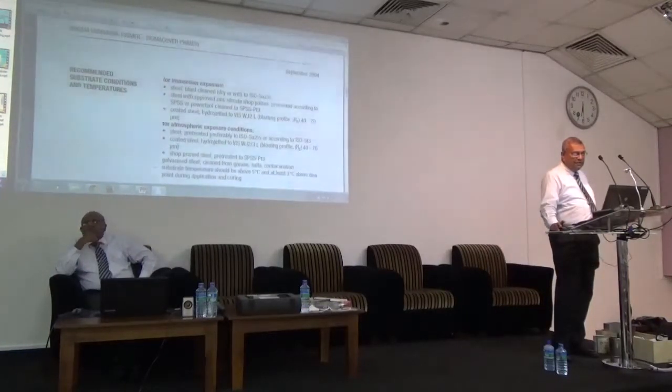People are reading. Now they say for immersion exposure, you have to steel blast clean to SA 2.5, then silicate primers, and say blasting profile should be 40 to 70 microns. Now what does it mean? You have this surface, you sandblast it to this, this is Rz, should be between 40 and 70 microns.